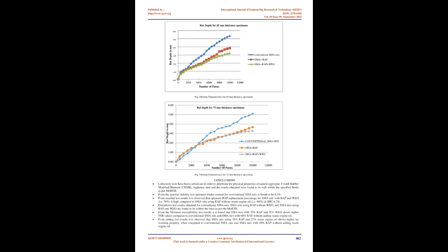The test is conducted for conventional SMA mix with optimum wrap material content and SMA with wrap material and bitumen modifier at 10%, 20%, 30%, and 40% of failure load which is obtained from its test. The apparatus, shown in the figure below, consists of LVDT, linear variable differential transducer, loading piston, loading frame, position controller, and data acquisition system with a loading rate capacity up to 5 tons.